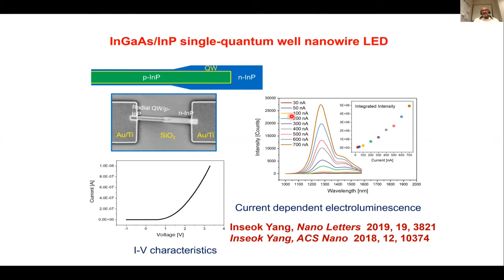And again, these are behaving like light emitting diodes, not like lasers, because there's no narrowing of the line width here, for example, which you would expect for a laser. But the good news is that they're emitting in the 1.3, 1.55 micron window region, which is important for optical fiber communications. But we are not able to get lasing. And we asked the question why.